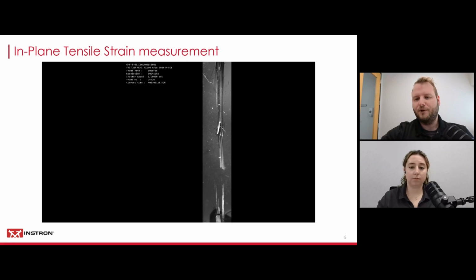For this test, the strain measurements were taken in the axial direction of the coupon, of the loading axis, and taken with a video extensometer on the front and with a clip-on extensometer on the back. The video extensometer, which is our advanced video extensometer, the AV2, measured the strain on the flat side here, and then on the opposite side we used the clip-on extensometer.